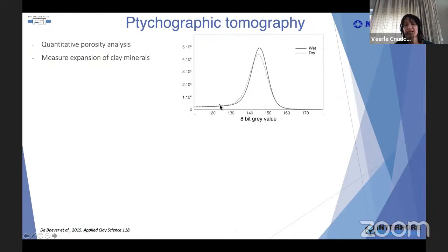So we could scan the material, then put it — you have the possibility to add a climatic chamber around your sample to control relative humidity and temperature. Then you wait until everything is stable again and scan once more. We tested the impact of wet and dry conditions on our sample, which was clay-rich.